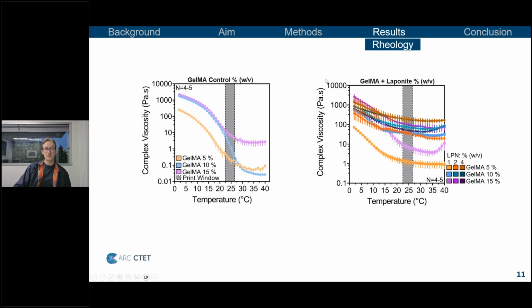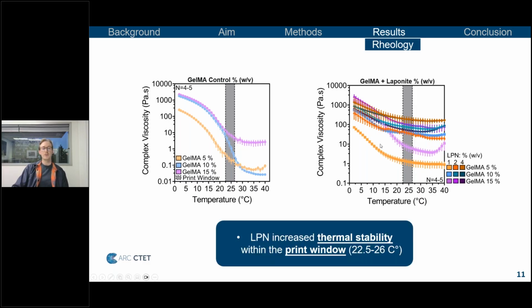And then we looked at the temperature sweep, looking at the control, where we would like to be able to print within room temperature conditions so we don't have to control the thermal conditions. We can see that compared to the controls, which increase within this range, with laponite, as you increase your laponite concentration, there is more thermal stability within this range and less fluctuation of your viscosity. So we can show that laponite increases thermal stability and reduces the viscosity fluctuations within your printing window at 22 to 26 degrees, which is ideal for what we'd like to achieve in print.